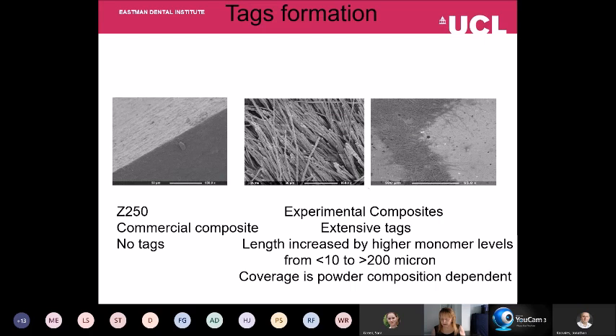If we take this dentine that's demineralised, place it on top of a commercial material, the two surfaces are repelled by each other. The composite is hydrophobic, it doesn't like the water in the dentine. Experimental smart composites, what these do is they penetrate in. If we want to get very long resin tags, we need to add in more monomer into the system. If we're at about 20% monomer, then tags are only about 10 microns. If we go up to 25%, we can get tags that are 200, even more, in length on the surface of the dental composite.